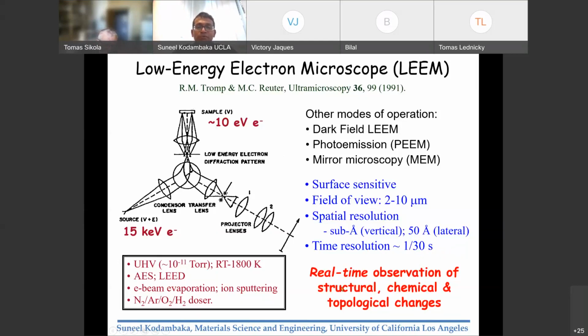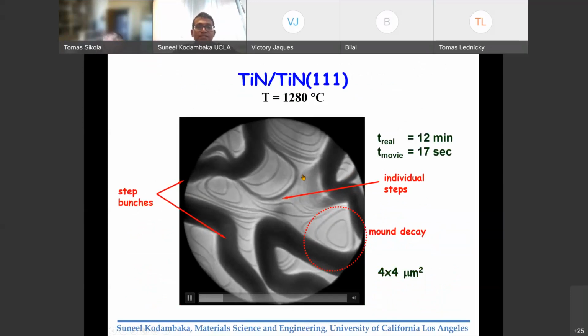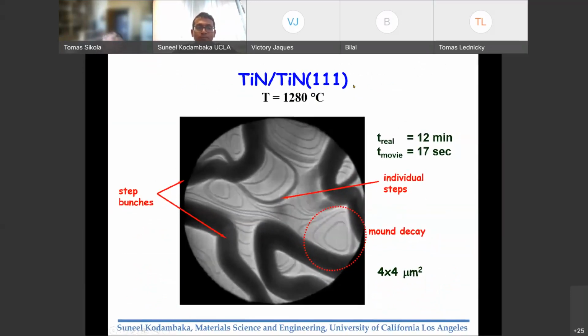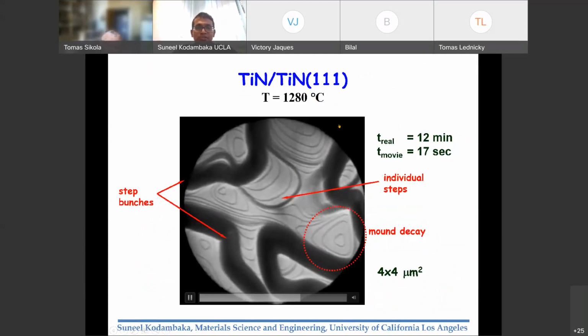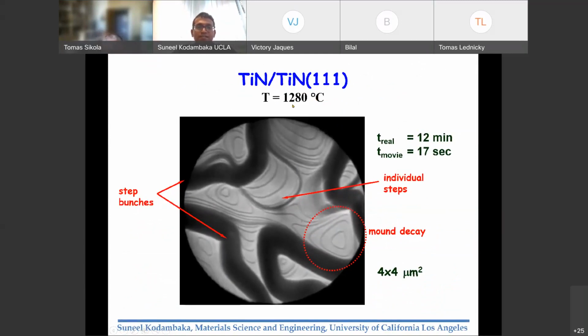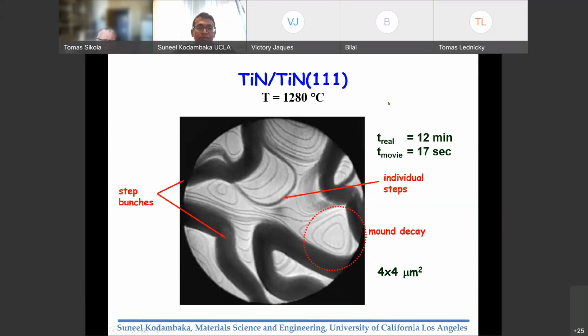I'll show a few examples of how the LEEM can be useful in studying surface morphological changes, and even to some extent quantify chemical changes. I'm sure some of your colleagues here are doing different types of studies where they follow surface chemical reactions and phase transformations as well. Okay, so for this study, we've chosen titanium nitride 111 and the annealing temperature. This is being annealed in a positive pressure of nitrogen just to make sure that we don't have any nitrogen desorption from the surface. This is done at about 1300 degrees C, and this field of view is about 4 microns.